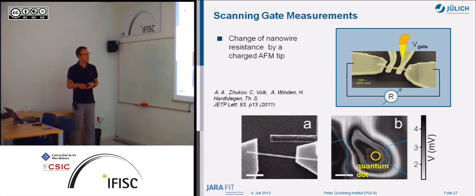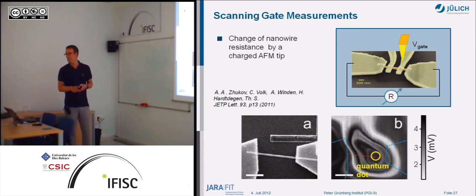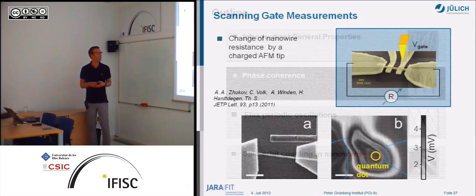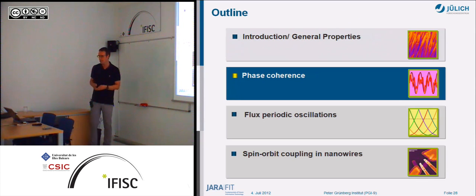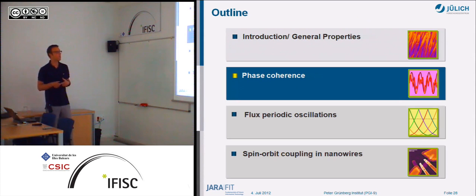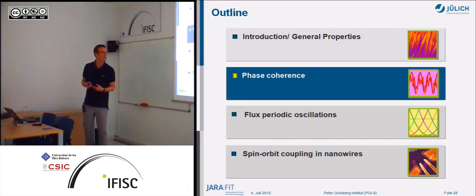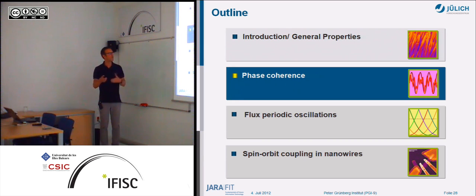Yeah, so here you can, by having these equipotential lines here in the transport. So this grayscale here is the resistance of the nanowire. Yeah? And so you see if you go in a circle around the quantum dot here, you get the same conductance here. Yeah, that tells you that the quantum dot itself is in the middle of the circle. Yeah, so that's a way to analyze in more detail and more locally what's happening in this nanowire. So this was all some introduction on how the nanowire works in general, how you can control the conductance of the nanowire, and how you can manipulate the nanowire.